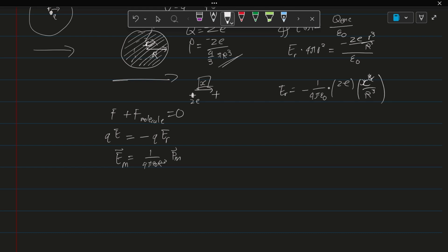So you could now obtain the polarizability. The polarizability, which comes from this Coulomb's law, is 4 pi epsilon 0 r cubed. So if you have a noble gas and you want to figure out the Bohr radius, technically the effective radius, you could just measure the dielectric constant by using the Clausius-Mossotti relation, get the polarizability, and obtain the radius. It's a very elegant tool, and that's only for the induced dipole moment.